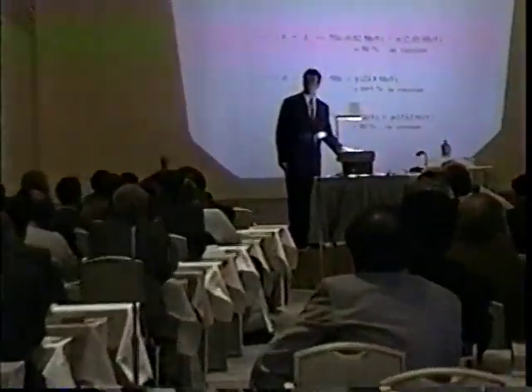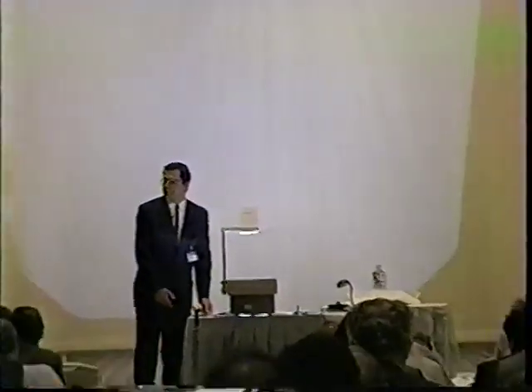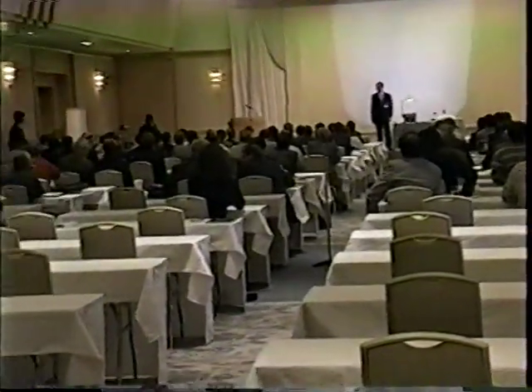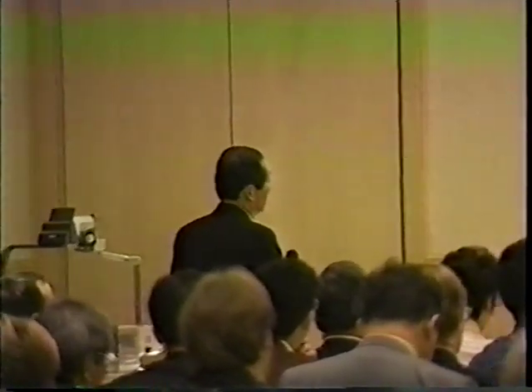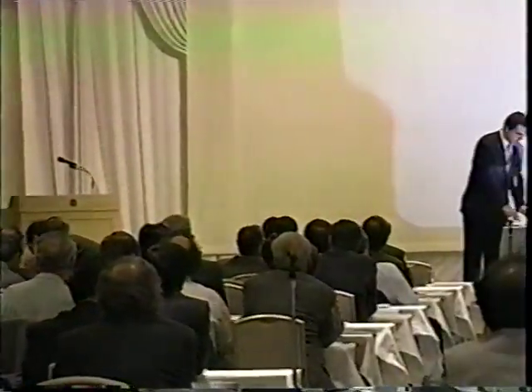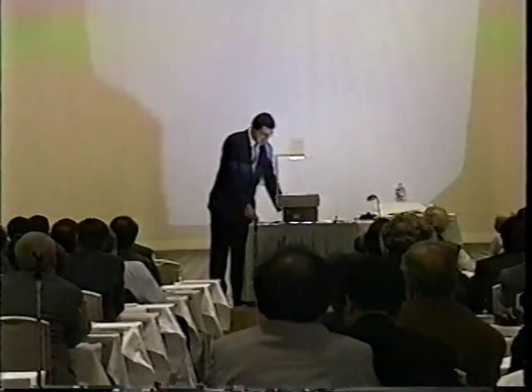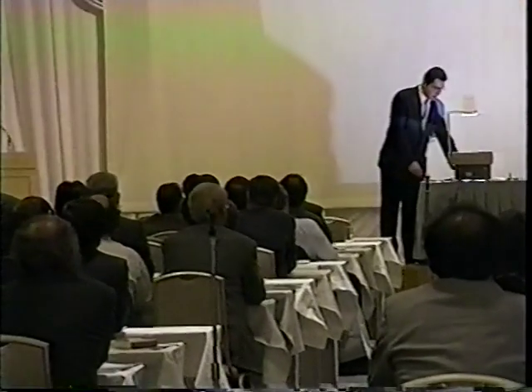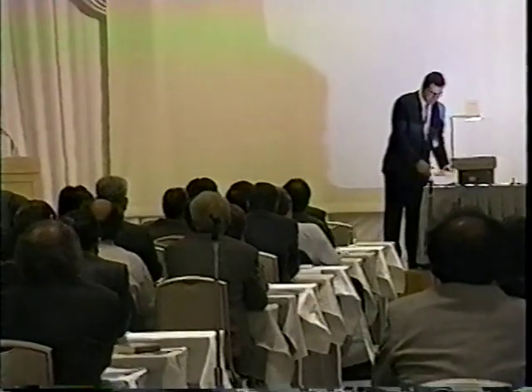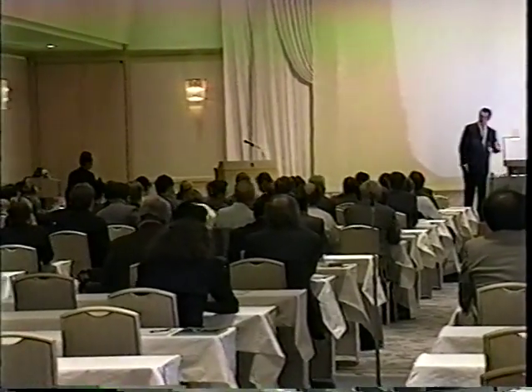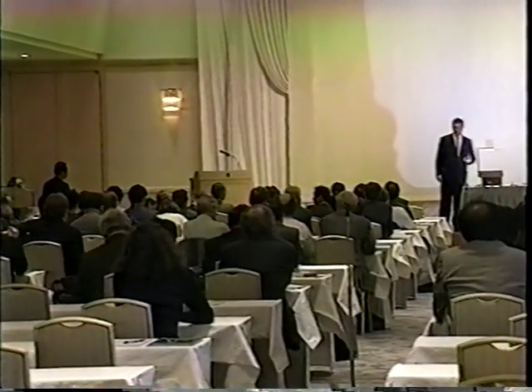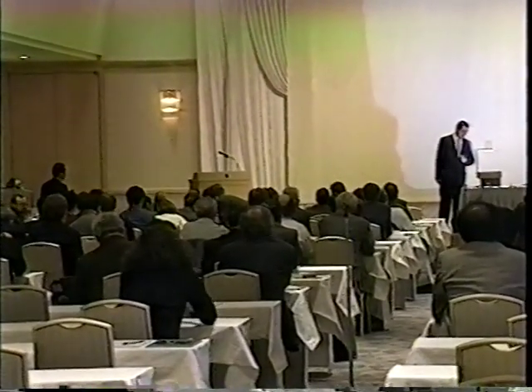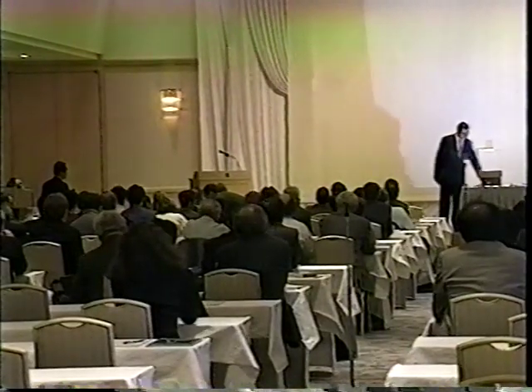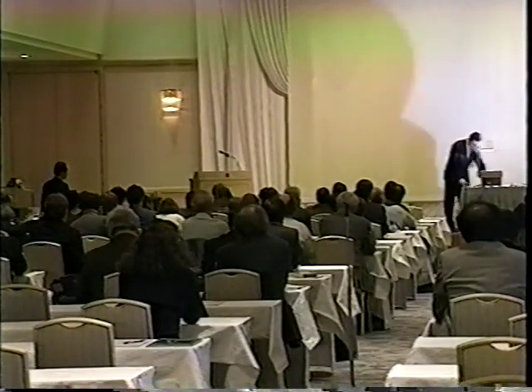Now, Professor Okamoto, please. Please let me know how to carry out the long-term loading ratio measurement. Have you some good idea to make? Yes. As a matter of fact, we did this kind of measurement in the older version of our apparatus, and the results we brought to Monte Carlo. With that low power value, we were able to measure loading ratio via a measurement of electrical resistance. In that case, the electrical resistance was a mean value taken reading a voltage between two electrodes. Our purpose for the future is to put through three,